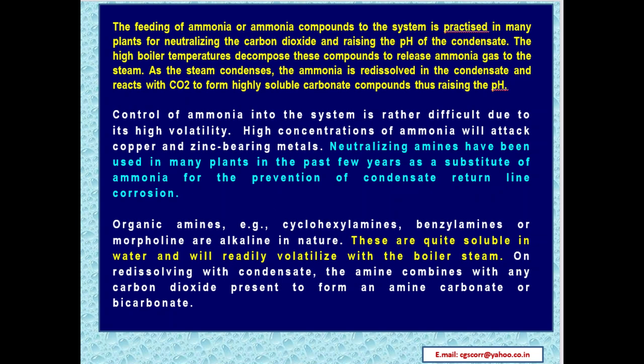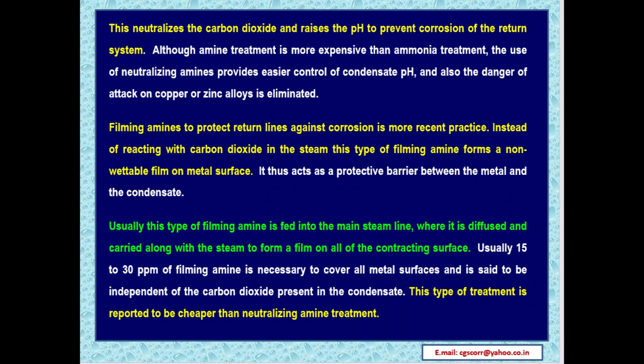Organic amines, for example cyclohexylamine, benzylamine or morpholine, are alkaline in nature. These are quite soluble in water and will readily volatilize with the boiler steam. On redissolving with condensate, the amine combines with any carbon dioxide present to form an amine carbonate or bicarbonate. This neutralizes the carbon dioxide and raises the pH to prevent corrosion of the return system. Although amine treatment is more expensive than ammonia treatment, the use of neutralizing amines provides easier control of condensate pH. Also, the danger of attack on copper or zinc alloys is eliminated.